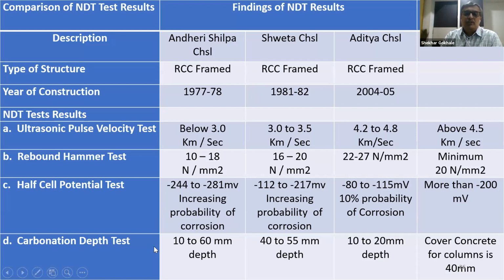And in carbonation depth also, there was variation noticed. In Andheri we got 10 to 60 mm depth. In Shweta the depth of carbonation is very high, 40 to 55 mm, which indicates the speed of corrosion will be high in this building in future. And Aditya carbonation depth was between 10 to 20 mm. So we checked 3 different buildings and compared the results, and they are more or less in line with the age of the building and their maintenance.